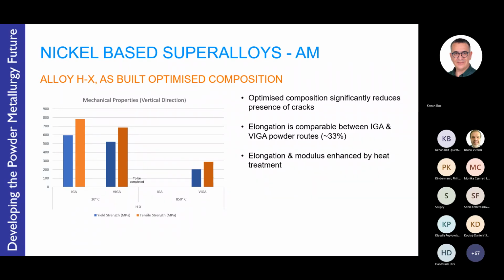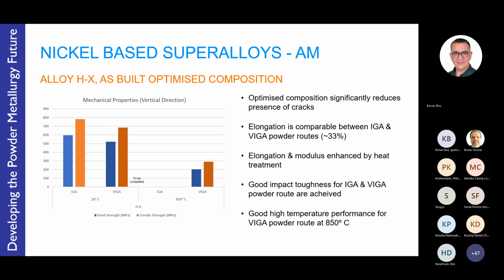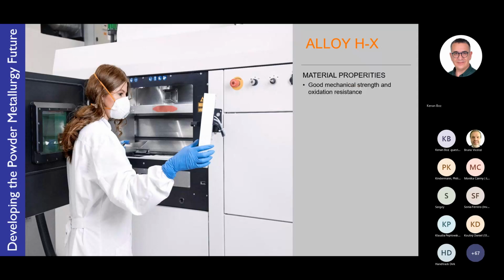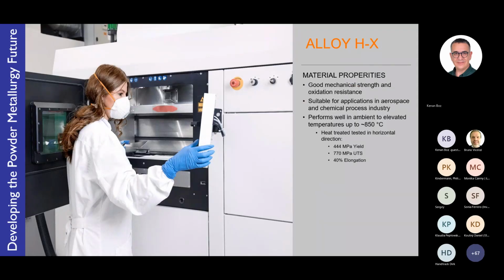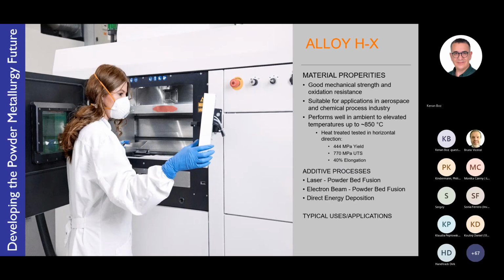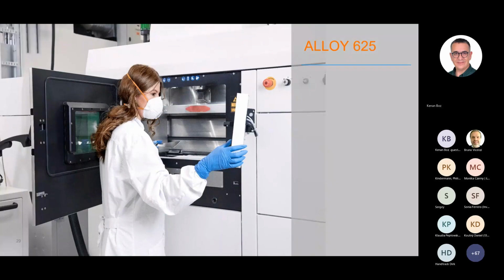Elongation and modulus was enhanced by heat treatment. Both inert and vacuum produced powders had good impact toughnesses. But really, when it comes to aerospace, having lower levels of non-metallic inclusions, there's definitely an advantage for vacuum melting. Again, producing a range of certified material properties operating at up to 850 degrees C. So yields and tensile strengths and high elongation, in this case up to 40%. And again, available for all the different additive manufacturing processes and relevant to aerospace applications.